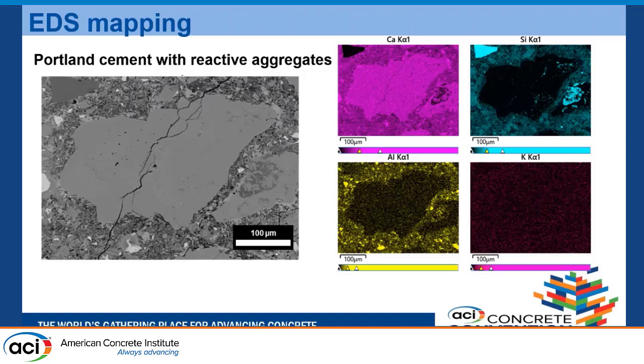The potassium that you see in the image is not an indicator that you have traces of potassium. You should have some maybe in the cracked regions or some spots. If you find traces in selective spots, that means we can do more analysis and look at the chemical composition. That may be an indicator of an ASR gel. So that is something I'll be doing. It's ongoing research, and it will be continued in the future.